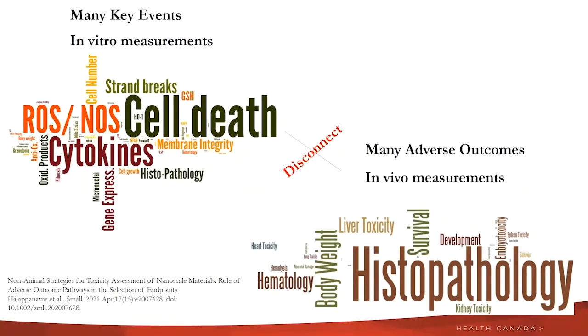But then a pattern emerges, and we took some of these key events and tried to understand how they connect with each other and what it means in terms of in vivo. The first and foremost thing for us was to go through this large literature database that we had, consisting of more than 10,000 papers, and identify these various key events in vivo and in vitro induced by nanomaterials, and anchor the in vivo measurements to an adverse outcome and the in vitro measurements to an in vivo response.